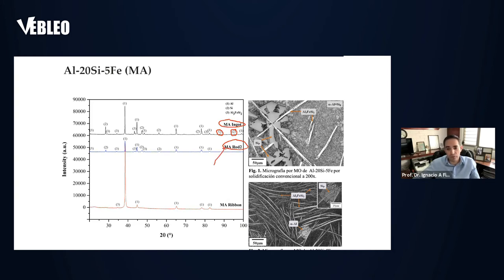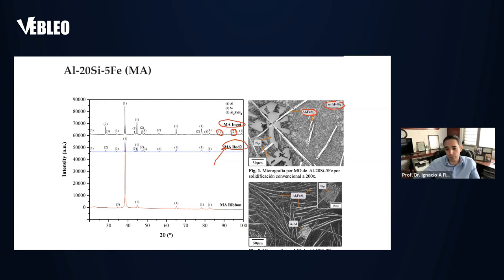Here we're cooling at around 10,000 or 1,000 Kelvin per second — a cooling rate achievable in industry — that's why we're using this method. This is the classic intermetallic for this alloy. This is the eutectic and this is the primary silicon, which also embrittles the alloy. We're expecting to modify this silicon in the microstructure in order to reduce this sort of morphology and improve the mechanical properties.